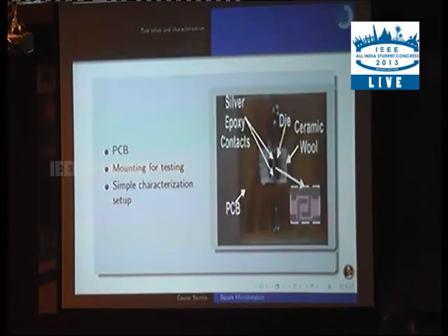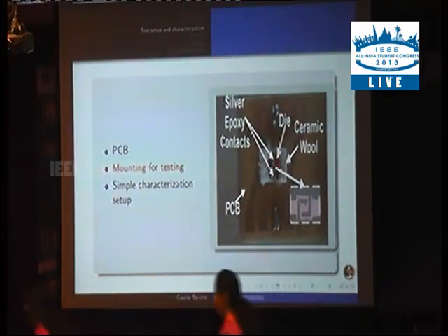Then our die is sitting, you can see the small die. It is sitting on a ceramic wool. Again, the ceramic wool is a very good thermal insulator. In order to reduce the thermal losses and to improve the power consumption, we have used this ceramic wool. You can see the contacts for these dies are made of silver epoxy paste.